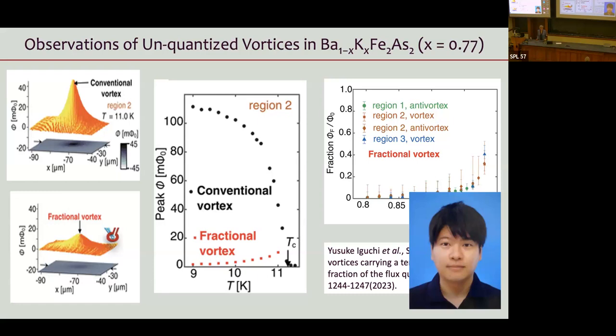So this is the latest example in which we've seen something, honestly, I would say really unexpected and really surprising, which is the possibility that in a multi-band superconductor there could be a complex order parameter in which the order parameter associated with different bands could acquire different phases that would allow for a flux quantum to exist in one of them and not in the others. And of course, we'll be doing follow-on tests that would confirm that this might exist and check out some of the alternative hypotheses related to inhomogeneity, although we've seen this at many, many different regions of the sample.